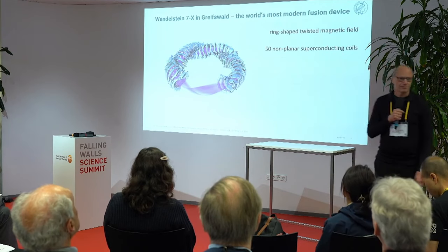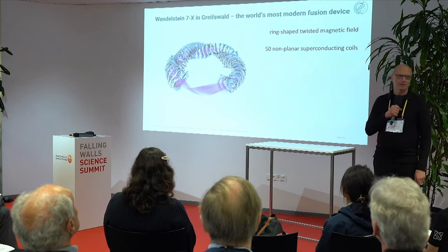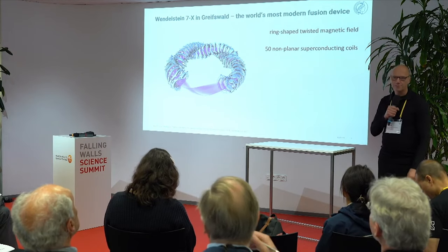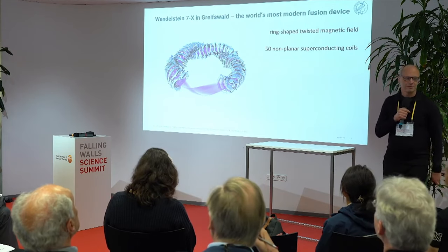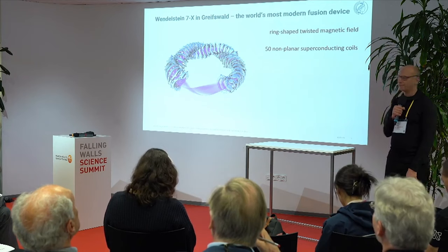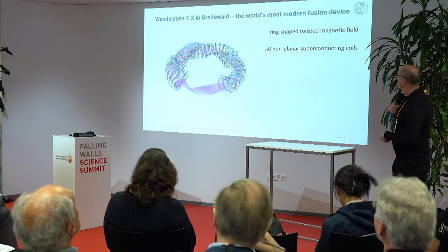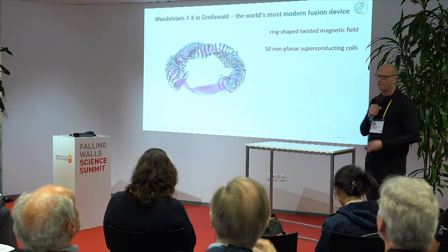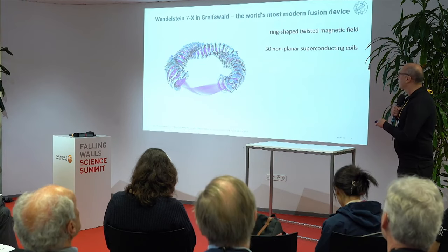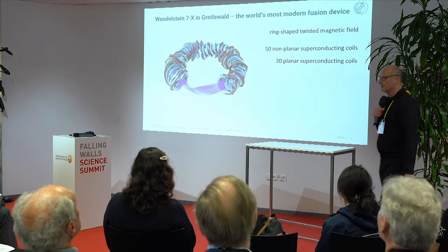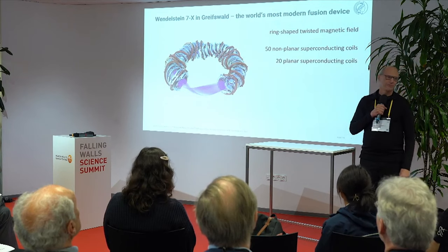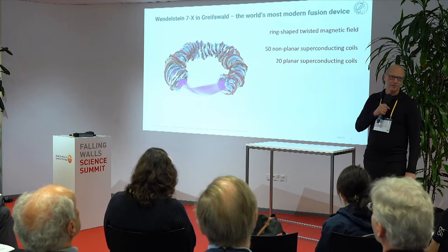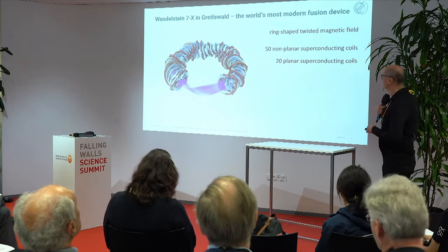that create this magnetic field shape, and a certain shape magnetic field means shape coils, full stop. It's just the inverse of Maxwell's equations. You can just calculate the coils. So these are superconducting coils, just normal superconductor, niobium titanium. And since we're experimental physics, we're also adding 20 planar coils in order to have more degrees of freedom to change the magnetic field, to vary the magnetic field.